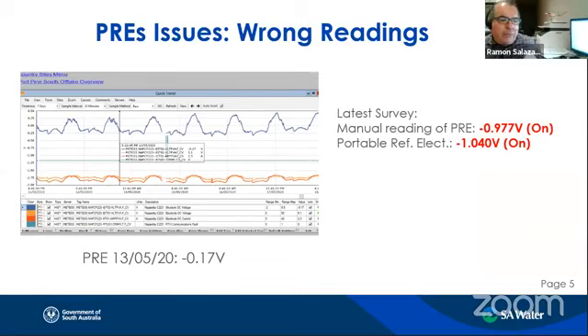We started to hear from CPTEX. Here is a water that they say started to see some of the reference electrodes stopped working. And they claim that probably that's because they dry out. For example, this is data taken from SCADA. I picked one day, 13th of May, the potential recorded by the reference electrode is minus 0.17 volts. However, the latest survey, I think in February, was on and off. It was minus 0.977 volts, on. And they used the portable reference electrode, minus 1.040 volts. This manual reading is, they took the reading directly from the reference cell on site.